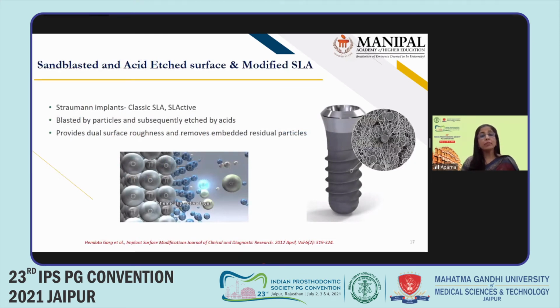So then came a combination of the surfaces that we discussed, which is the sandblasted and the acid etched. So the implants were first sandblasted, and then acid etched. These implants are also termed SLA implants, and these surfaces are first blasted by the sandblasting particles, and then subsequently etched by the acids. So what does this do? It creates a dual surface roughness, and most importantly, you're expecting some residual sand particles sticking over the surface of the implant because of the sandblasting. The acid etching carried out after the sandblasting basically removes the embedded blasting particles.